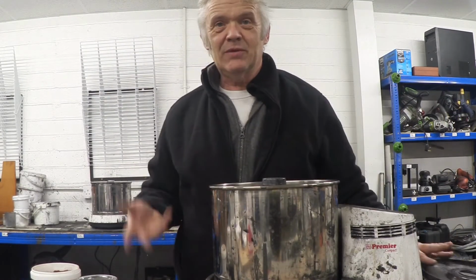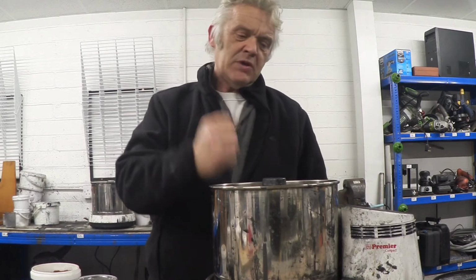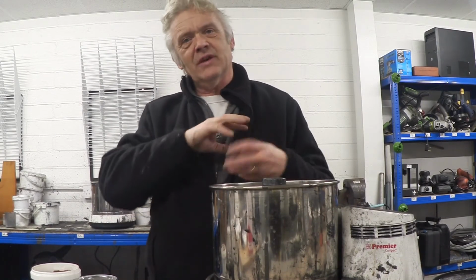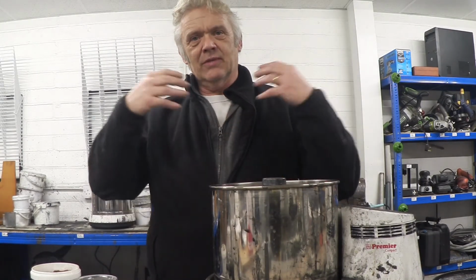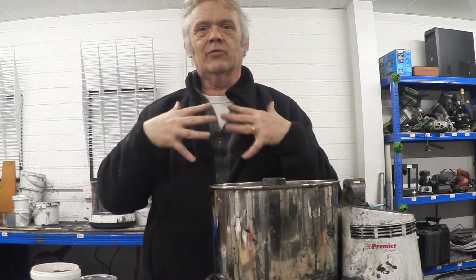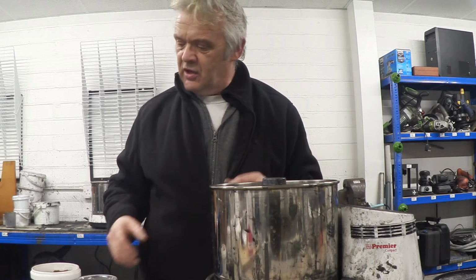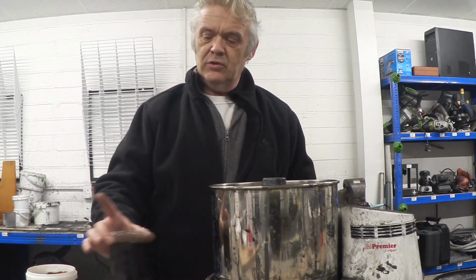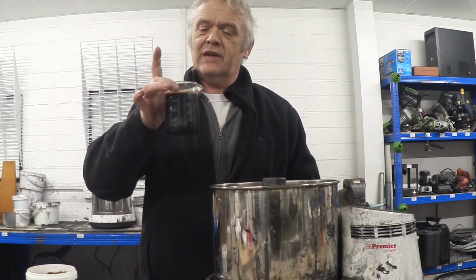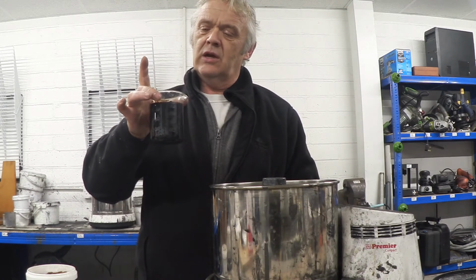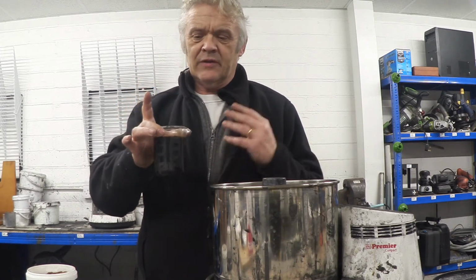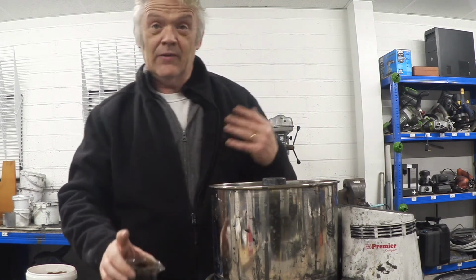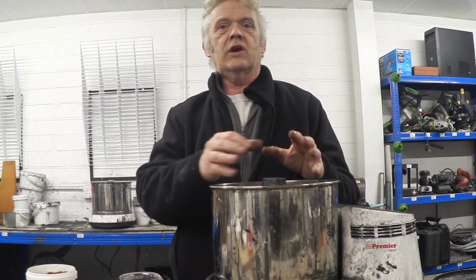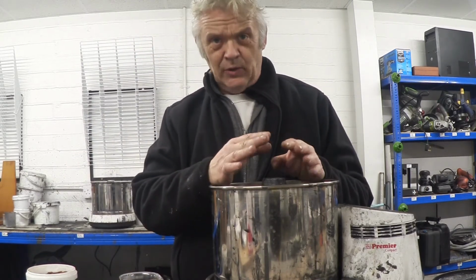Okay, so it is a slow and noisy process, but this has been going for a few hours now, and that makes everything mix up rather nicely and makes all those fibres interlink with all the protein fibres. What we're going to do now is cross-link them. In order to cross-link them, we use this stuff. This is tannic acid, and it's dissolved in a KOH solution. Now there's 6 grams of tannic acid in there, and that's 10% by weight to the casein that we put in here. It's quite a lot.